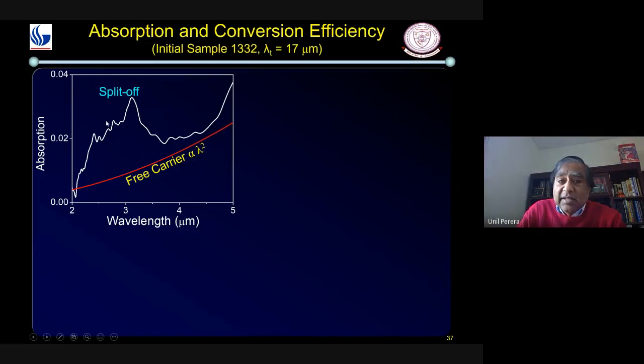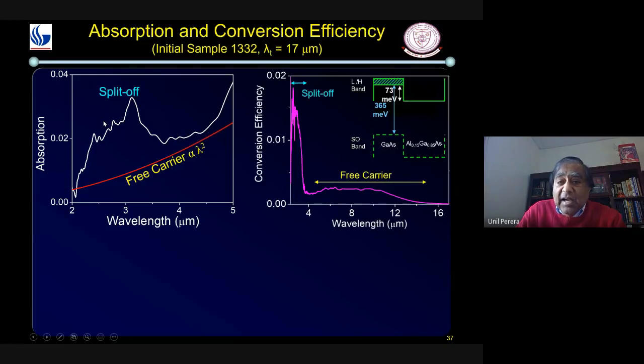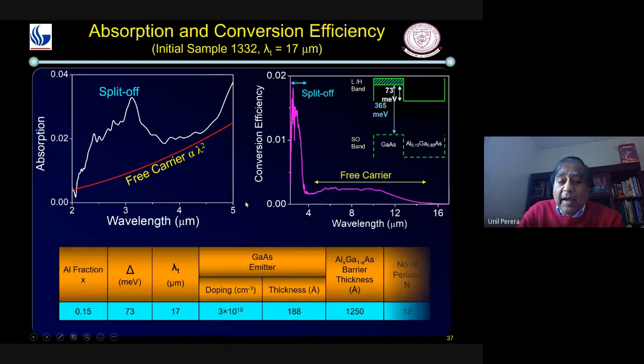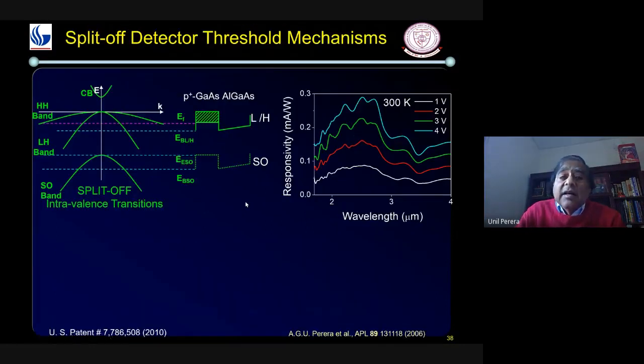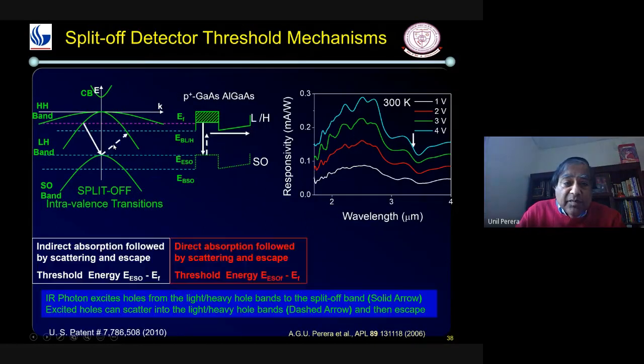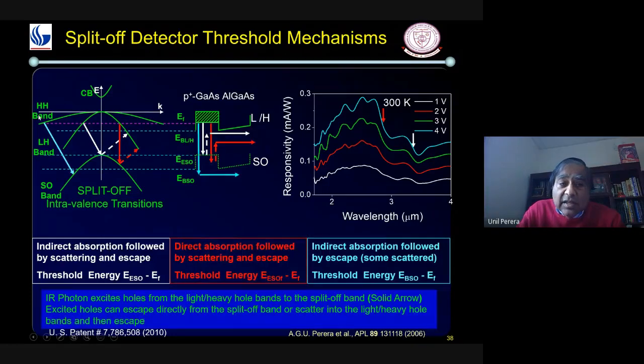So we realized that because this is p-type, this is a split-off energy. And that was very strong compared to the free carrier. So this is the full range of that detector. Free carrier part is here. This is the split off. And so this is the split off mechanism, how it works. The heavy hole, light hole, and split off band.